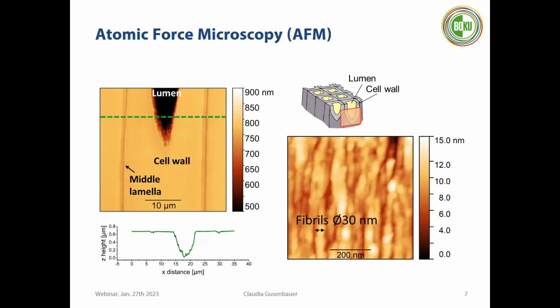So the AFM that we have available at our institute, we can measure in XY direction, in the image size, up to approximately 100 micrometers. And in Z direction, in this height code, we can measure maximum up to plus minus 6 micrometers. So we're really limited in a way that we have to have flat substrates for our measurements.